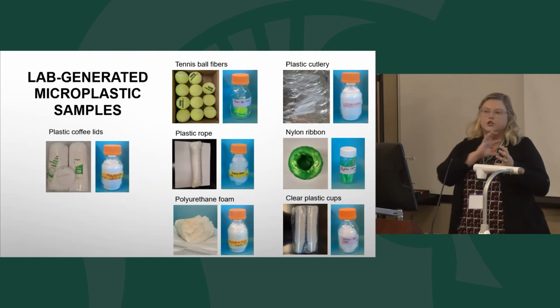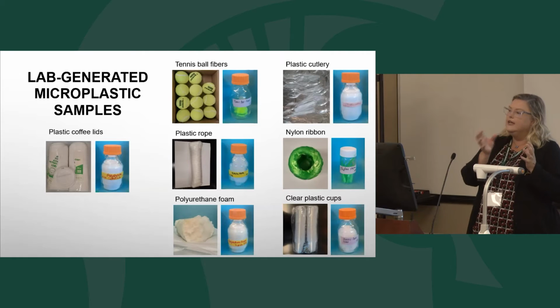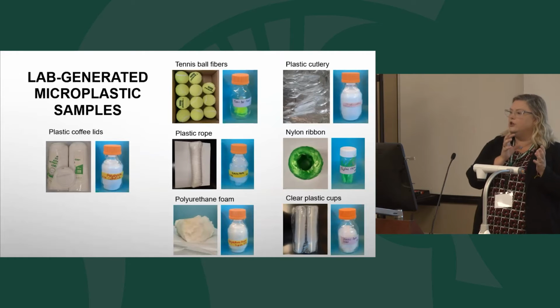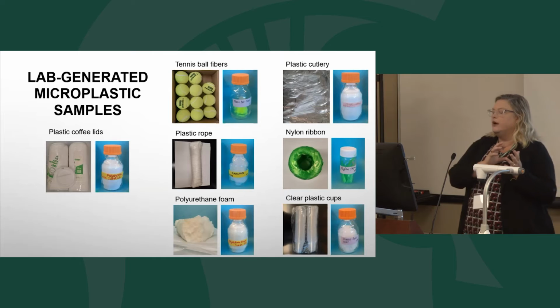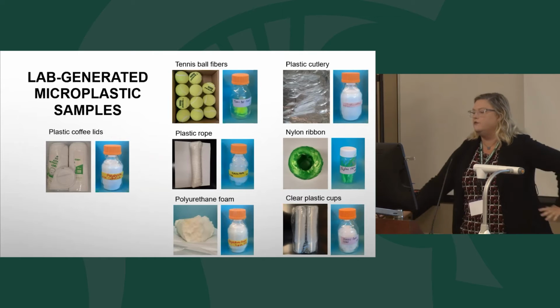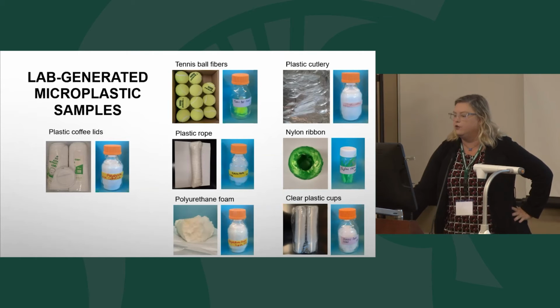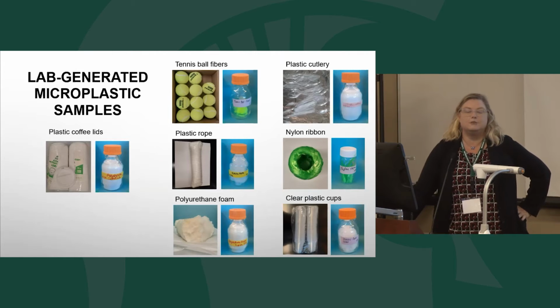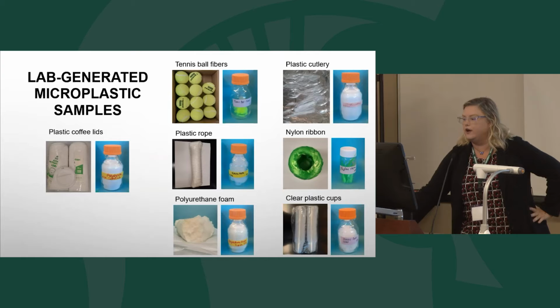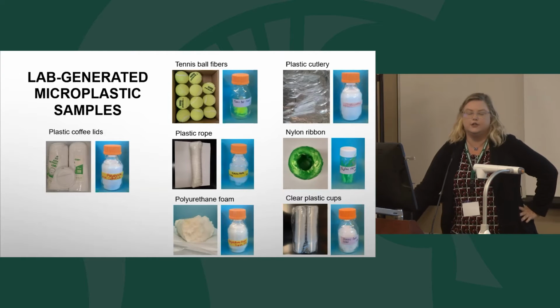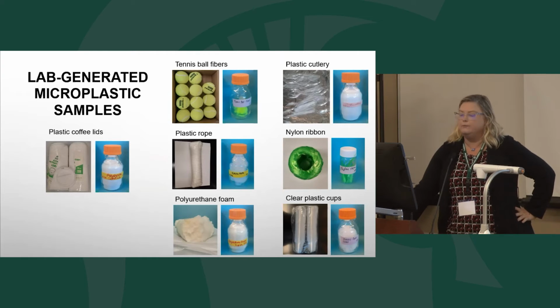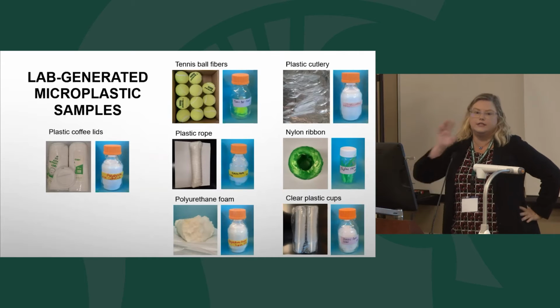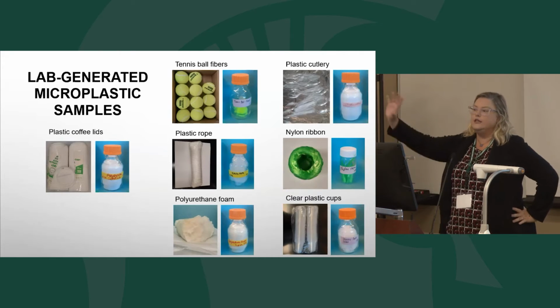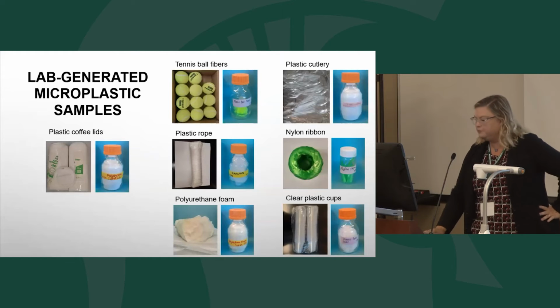For the fiber ones, we're actually using a zester, you know how you would make lemon zest or zest your orange for cooking. We're using those grates to be able to get the fibers off, and then we flash freeze them and grind them further. Ropes, polyurethane foam, and packing peanuts are some of the easier things to grind and get to an ultrafine powder without having to move past the blender. We can use the kitchen grade blender just to get all the way down to very small ultrafine size particles without having to subsequently take it to the grain mill or then take it to the planetary mill after that.